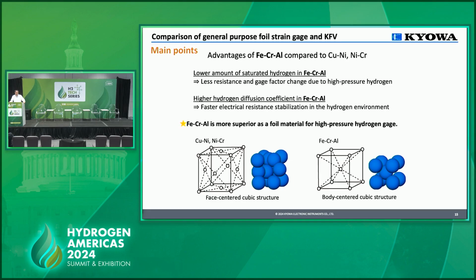On the other hand, the copper nickel and nickel chromium alloy foil typically used for general purpose 4-strain gauges has a face-centered cubic structure. This more densely packed geometry has a higher atomic packing factor compared to the body-centered cubic structure. So more hydrogen atoms will be trapped and get stuck in the cubic structure, which in the end causes more hydrogen embrittlement in the gauge sensing element.